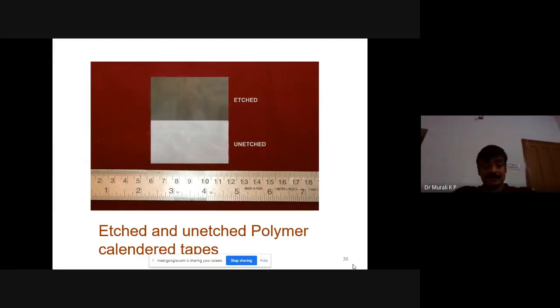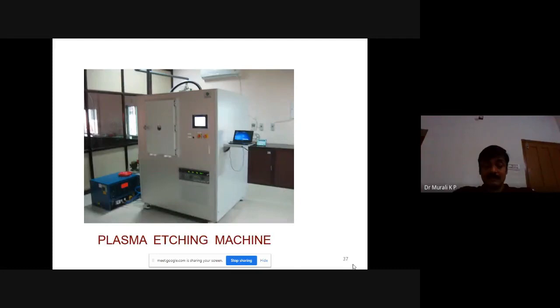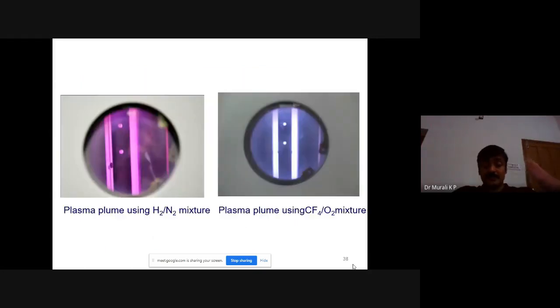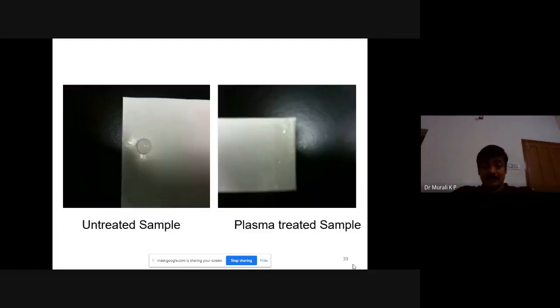Another process, which is industrially accepted, is the RF plasma etching machine. We can generate plasma using different combinations like hydrogen nitrogen or CF4 oxygen mixture, and this surface can be etched. Once the surface is etched, how do we test that? Just put a drop of water.